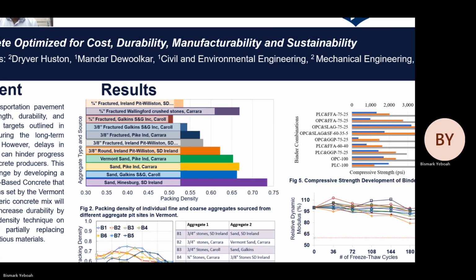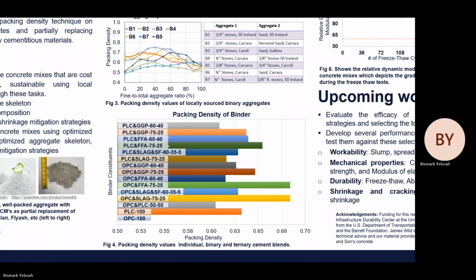Figure 3 shows the packing density of binary aggregates, that's the combination of two aggregates in a ratio of 0 to 100%. Blend B1, which is a combination of 3/4 inch stones from SD Ireland and sand from SD Ireland, had a maximum packing density of about 0.75 at 40% fine to total aggregate ratio, followed by B4, a blend of 3/4 inch stones from Carrara and 3/8 stones from SD Ireland, which had a packing density of about 0.74 at 50% fine to total aggregate ratio.